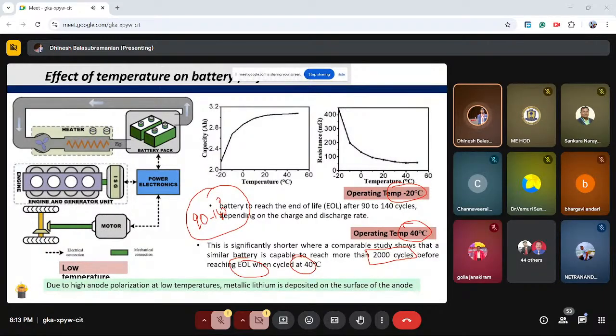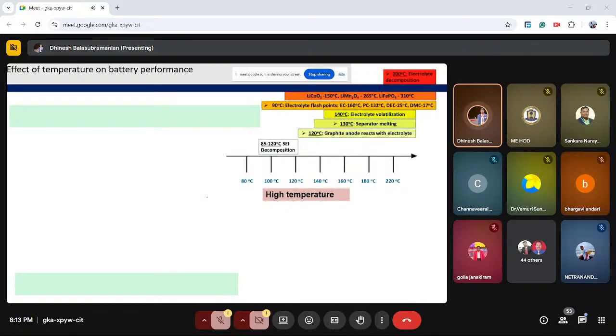And this is for the low temperature condition. Due to high anode polarization at low temperature, metallic lithium is deposited on the surface of the anode, or whatever pathway the lithium travels within your cell. So it will travel from one side and won't get back to its original state. It will stick on the different paths that it generally travels. So this is for the low temperature case, and we will look in detail at what would happen in the high temperature case. As I said earlier, the optimum temperature range is 15 to 35 or 40 degrees Celsius. But in general, you can operate your lithium-ion battery from 0 to 60 or 65 degrees Celsius. The lithium-ion battery is able to work in this window effectively, no issues. But it is always preferred to stay in the optimum range.